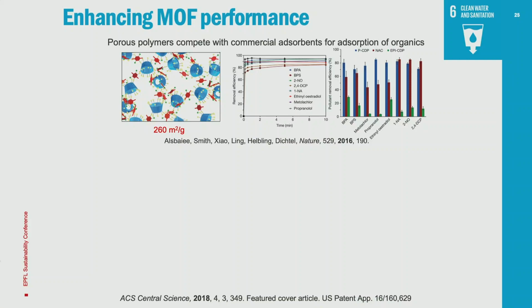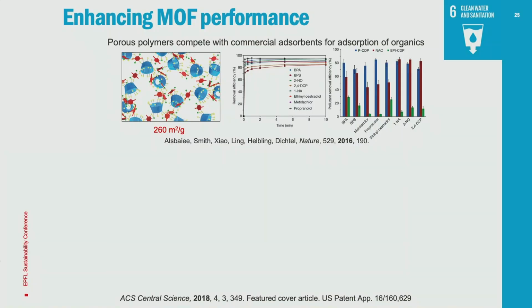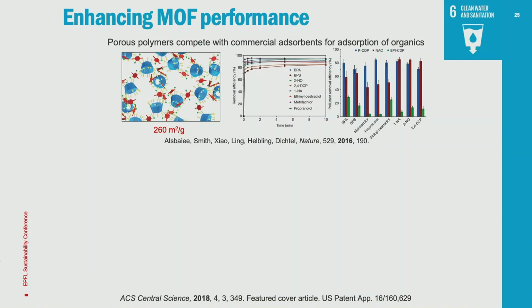And so what they showed here is just a polymer, okay? What they did is they put in this blue, this is just a cyclodextrin. It's a sugar-like molecule. And then these are interlinked by rigid organic molecules, okay? What they showed, the really fantastic thing about this paper, is in the second plot, you see that it removes many of these harmful organics at a very rapid rate, okay? This is really important. Then they compared their removal efficiency of their material in blue to an activated carbon, which is a common commercially used material, and then also another material which has the same exact building blocks nearly as theirs, shown in green.